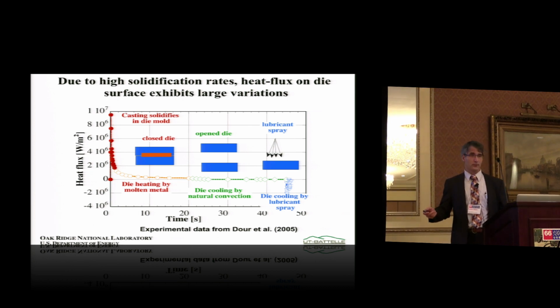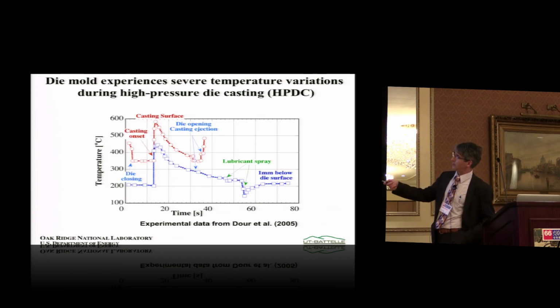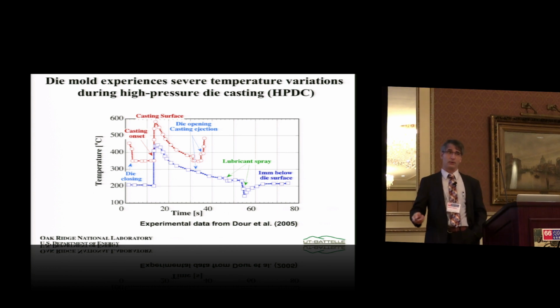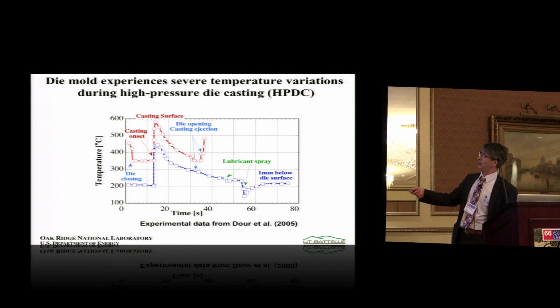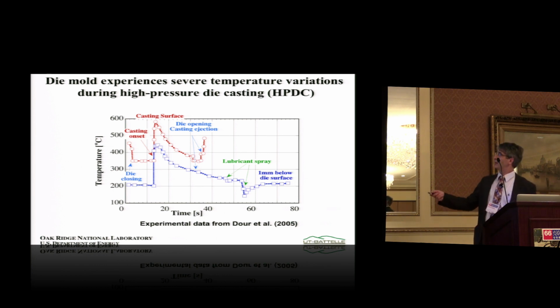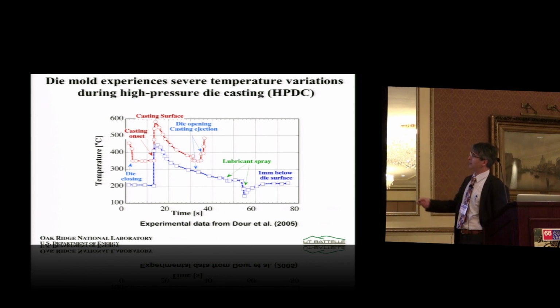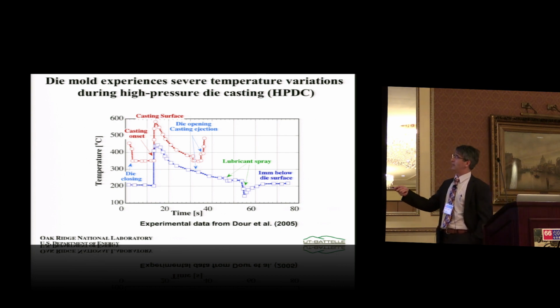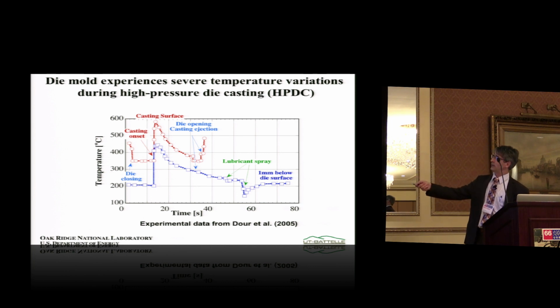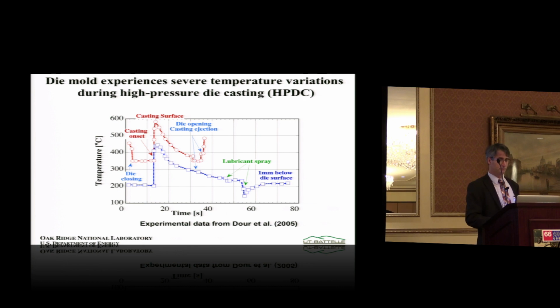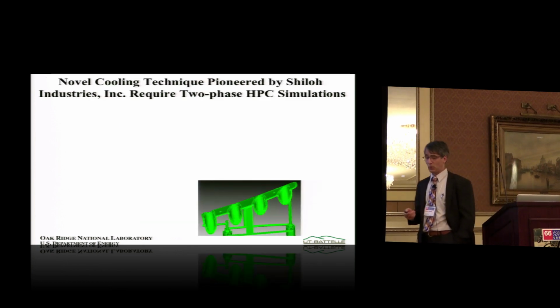During this very high heat flux, the die itself experiences some very high swings in temperatures. In this particular example, the die temperature actually was measured with a pyrometer, and the cutoff for that pyrometer is 350. So actually the swings in temperatures are from about 200 up to almost 600, and that happens with every shot. And you can see here different parts of the process: when the die is closed, when the billet is injected, then the die opens, and the casting has to solidify within that 20 seconds time frame. So how are we going to cool that die?